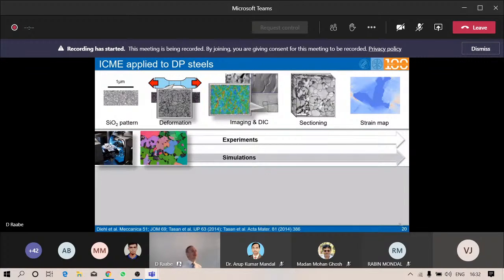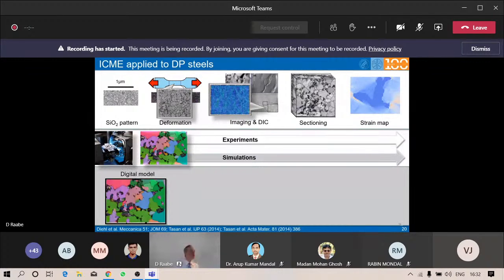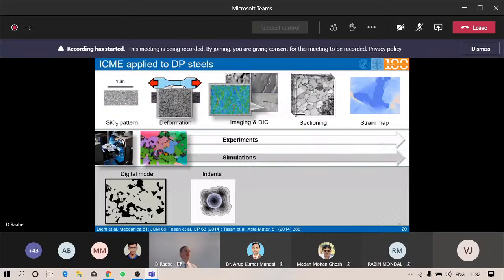Now on the simulation side, where we try to mimic that with DAMASK, you first render your microstructures of interest digital. That can be typically done by different methods associated with pattern recognition, with machine learning, or simply using certain features from the EBSD results, like surface pattern quality. And then you have to retrieve, in this case by indentation, for instance, the single crystal mechanical data that you need. But we also have macroscopic inversion methods from which you get the single crystal data that you need for